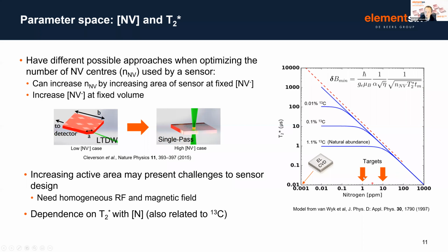What I'm going to focus on are two target levels of nitrogen in the material that we've been developing. One exists around 1 part per million nitrogen, which is a logical concentration to choose because in the natural abundance case, this is the maximum concentration that we can use before this coherence time starts to drop off. And then the other target that I'll focus on is around 10 ppm of nitrogen, where again, it's reasonably favorable in natural abundance, but we can start looking at whether there's other ways of us recovering the coherence time that we've otherwise lost by increasing the nitrogen concentration.